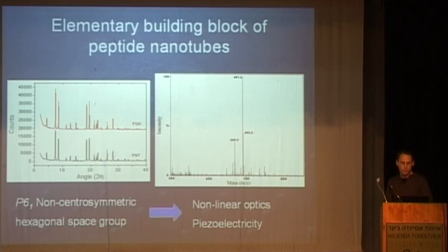So we thought to ourselves, we have a crystalline structure. I have a nanocrystalline region. I used some quantum mechanical equations. I didn't want to put them. It's way too much for this time of the day. And all the nanocrystalline regions are of the order between 10 to 13, 14 angstrom, only slightly above 1 nanometer, which is very small. And we have a P61 non-centrosymmetric space group.